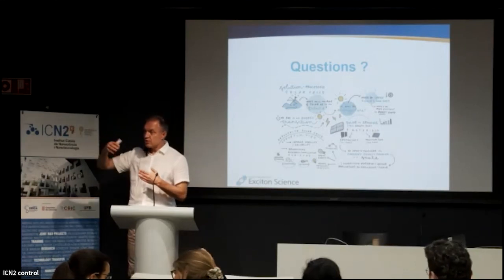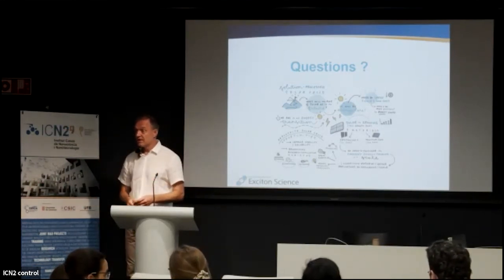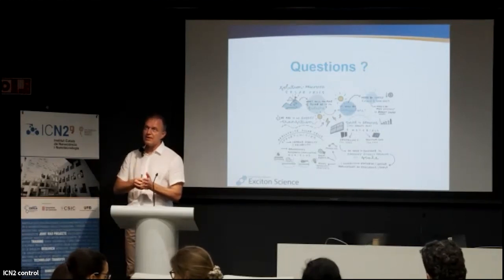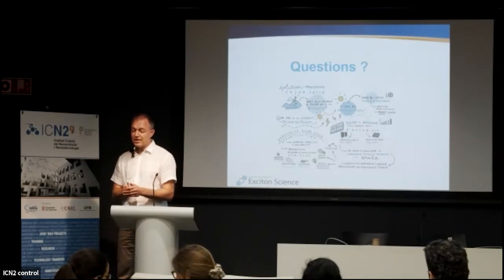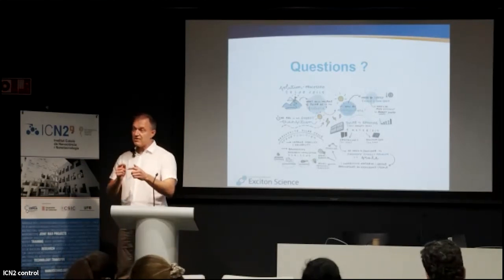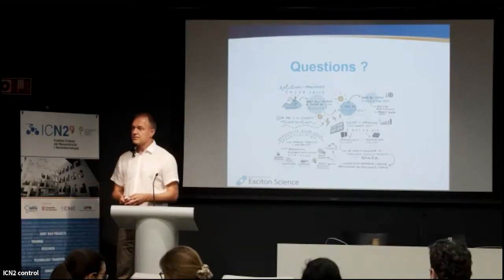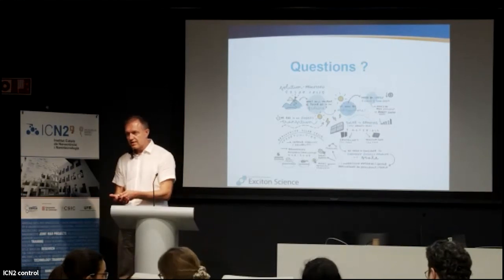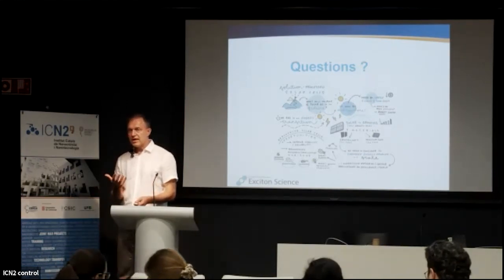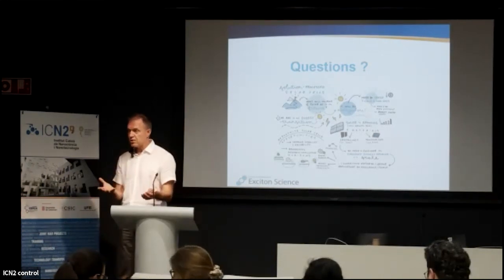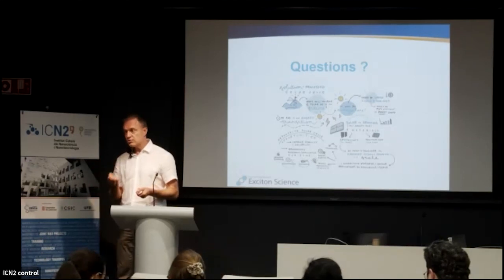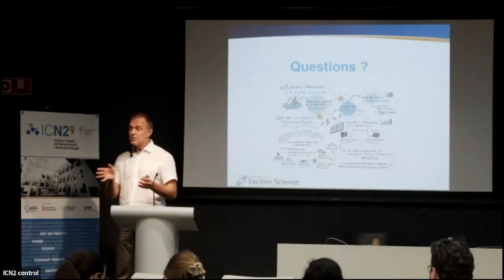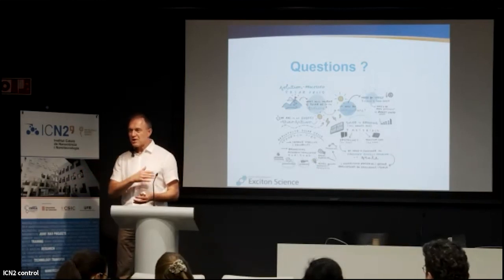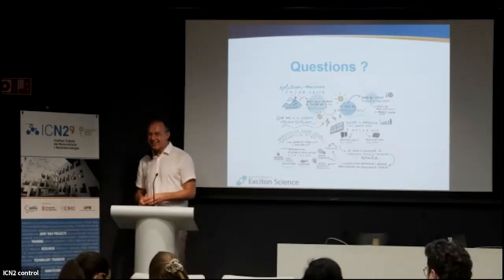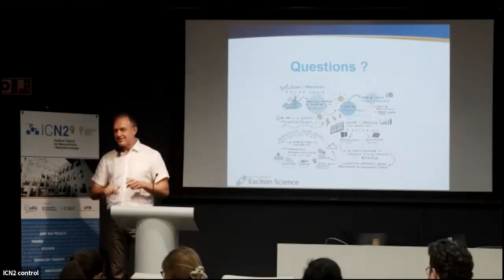So we start at 10 watts per square centimeter. That's already a factor of 100 away from the sun. You have to go to 1,000 suns to have the remixing. If you think, for example, of a solar concentrator, can I have a solar concentrator where the light intensity is high enough so that whatever phase segregation phenomenon I have can be reversed? You would have to go to these very high intensities. It's my mistake for calling it low and high, because you were thinking indoor, which is much less than what I was showing here.